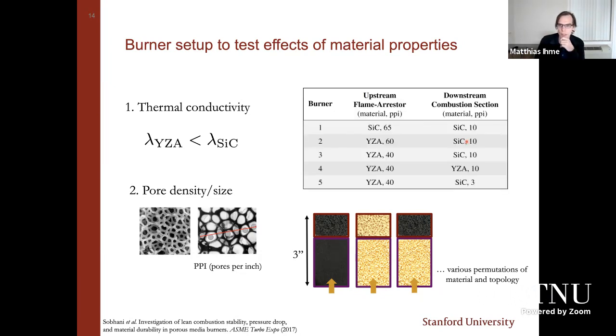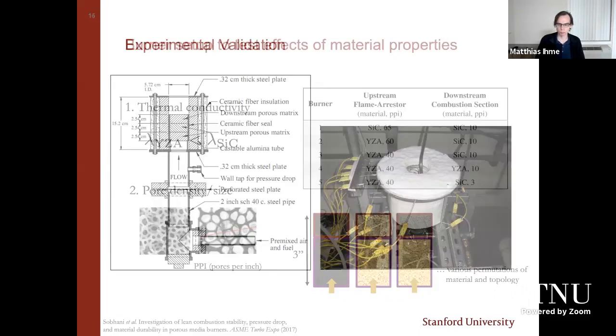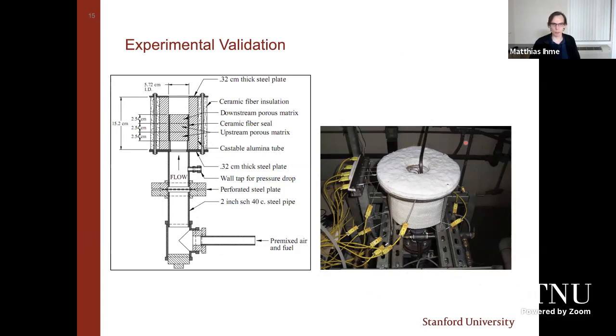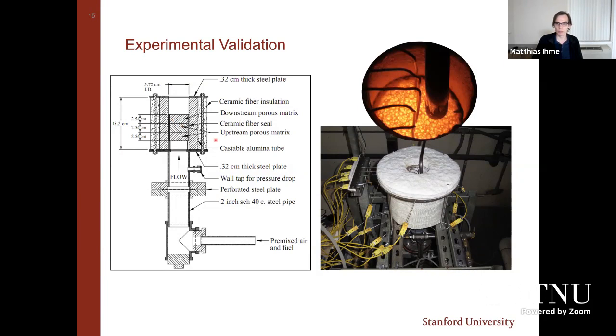Okay, to illustrate this, we have done different experiments with different materials in the upstream flame arrestor, where we're using silicon carbide and this YSZ, yttrium stabilized zirconia. And in the combustion region, we're primarily using silicon carbide. So what I'm showing you here is a conventional burner setup. It's a rather simple setup where we are injecting a premixed fuel air mixture. You may recognize the 3 porous media burners here. They're insulated, and if you look at the system, the flame would essentially look like this red glowing system.